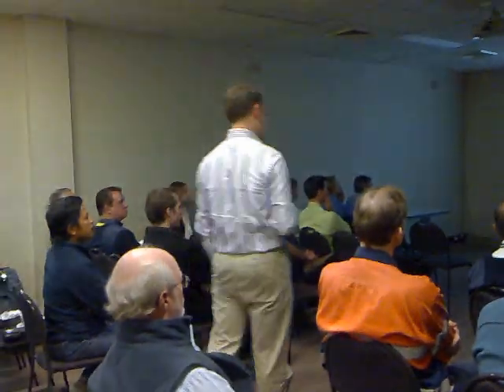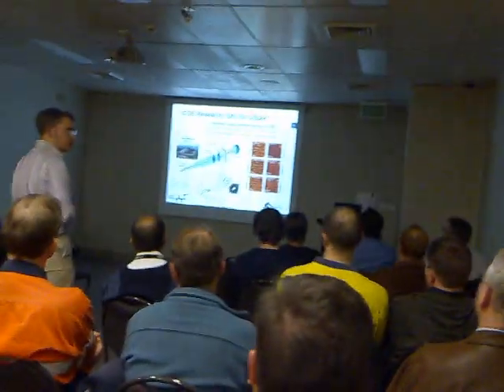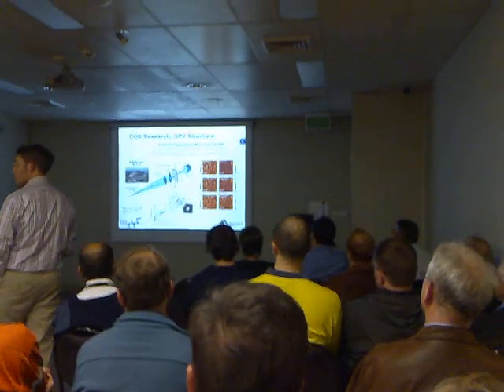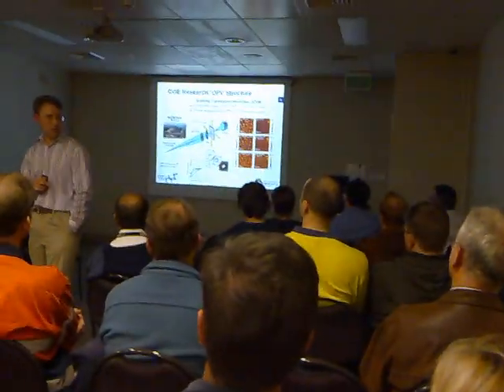Because these materials have a very characteristic absorption — they have a little fingerprint in their X-ray absorption spectrum. At a synchrotron, I've got stacks of X-rays, which means I can focus them down using a Fresnel zone plate to create a spot on a surface that's only around about 25 nanometers across. Imagine — it's like having a little torch, an X-ray torch, where the spot is 25 nanometers.